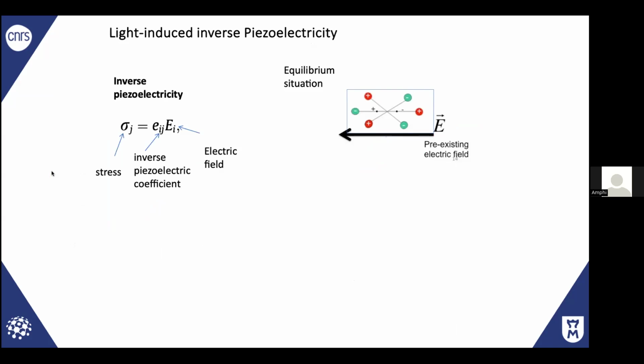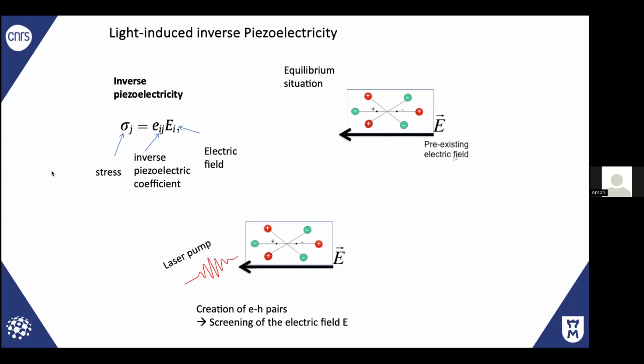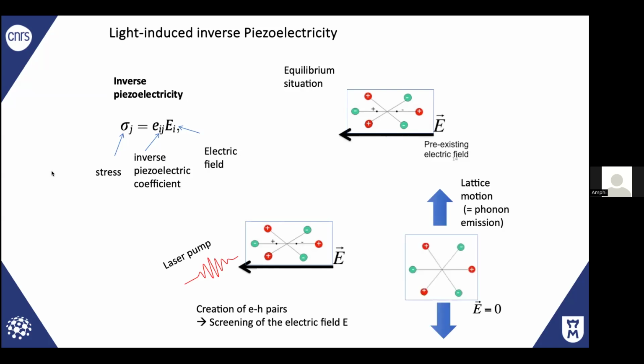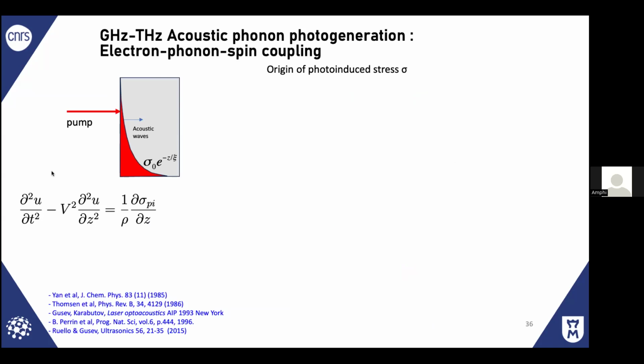What is the piezoelectric effect? It's basically something that happens in all non-centrosymmetric materials. As soon as you have an electric field in such a non-centrosymmetric material, if you modulate that electric field, you can induce a stress or strain. So basically this is that situation. If you shine light in a system where there is a pre-existing field, and you create an electron-hole pair, you can screen that electric field. In that case, the lattice relaxes and emits phonons. This is the inverse piezoelectric effect. This is what people know from piezoelectric transducers. But in that case, as I will show you, we can trigger it by light, by injecting electron-hole pairs in some depletion layer of semiconductors.